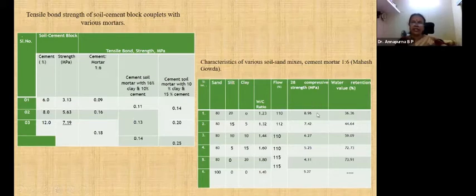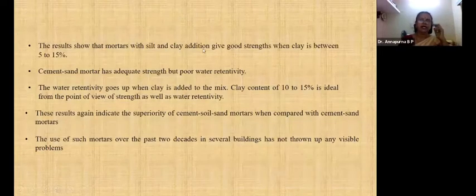For the 28-day compressive strength, it is found that 0% clay shows 8.96 here, and with the presence of clay it has been reduced: 7.4 to 6.4. And here the water retention value is also increased with the presence of clay. The result shows that mortars with silt and clay addition give good strength when clay is between 5 to 15%.